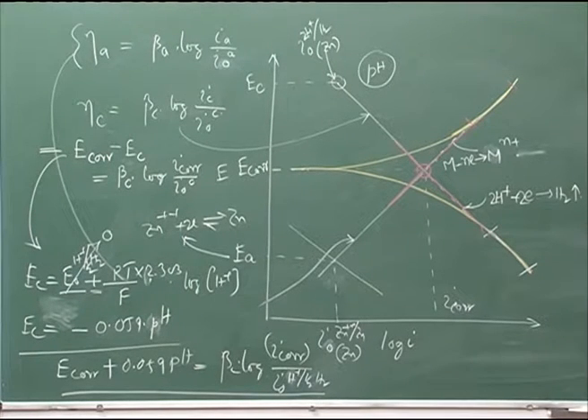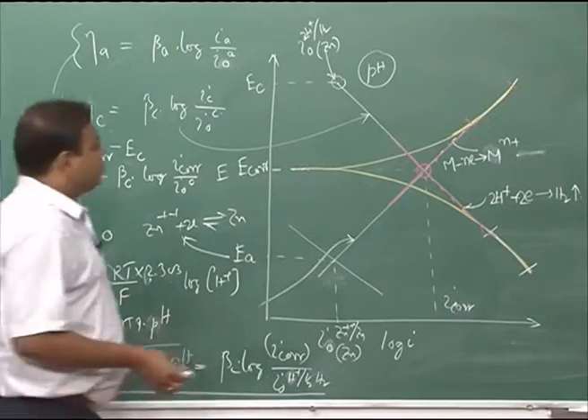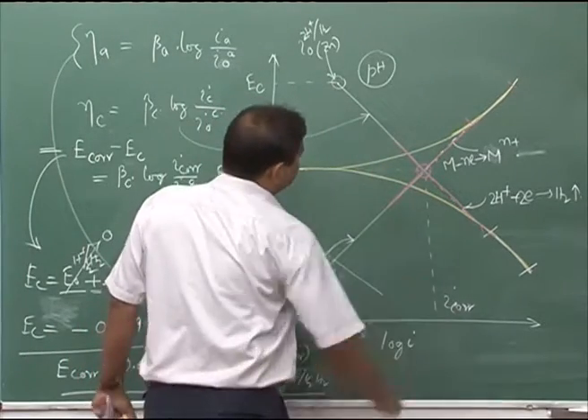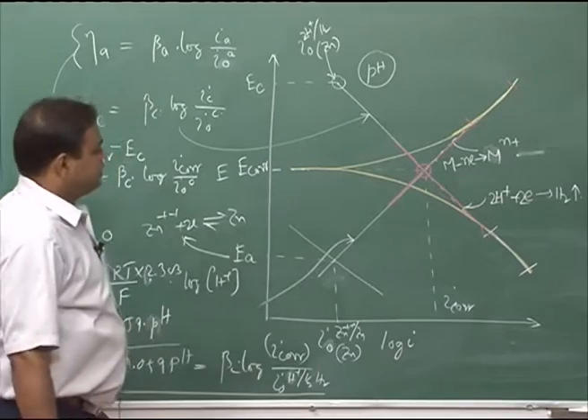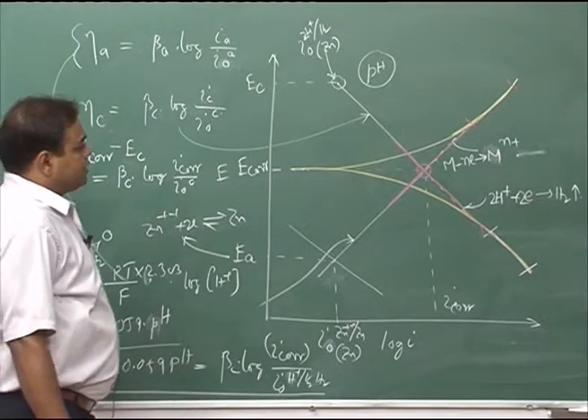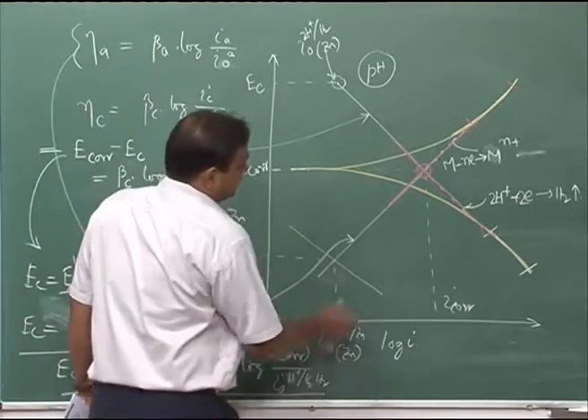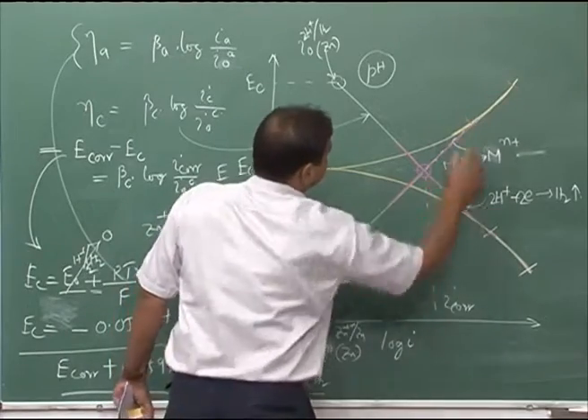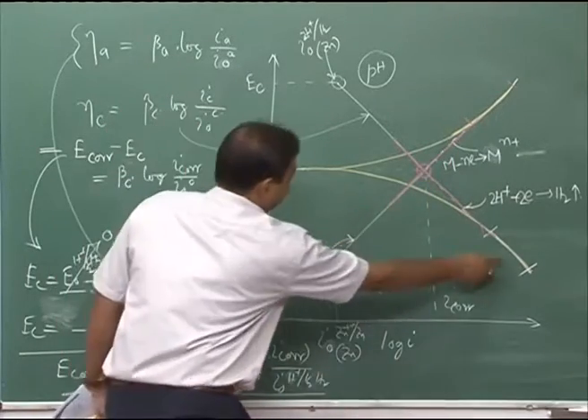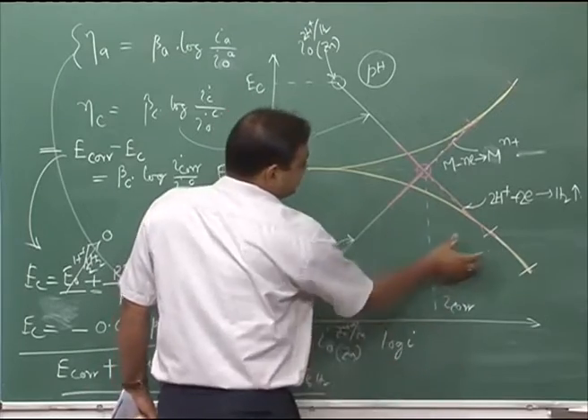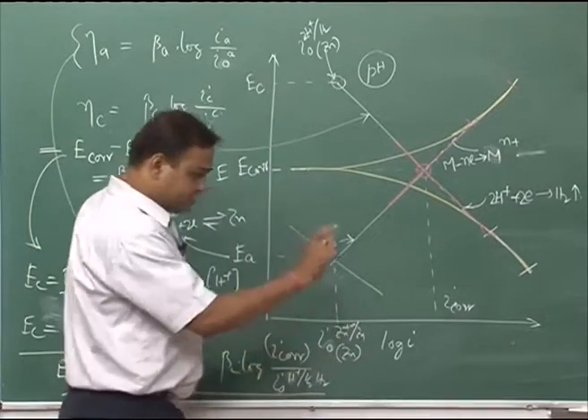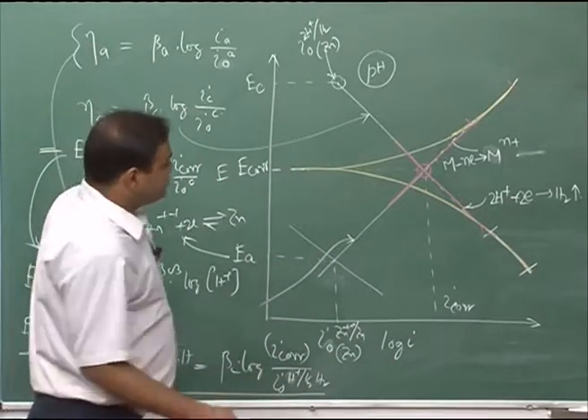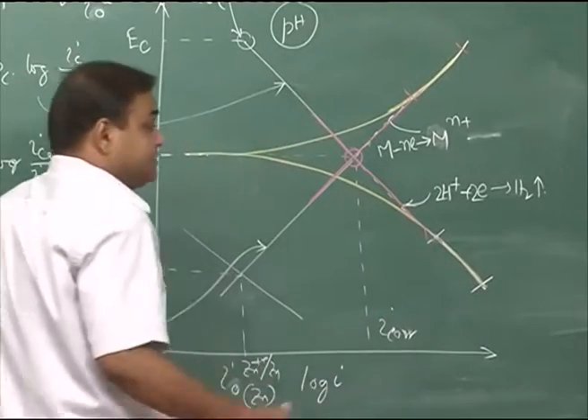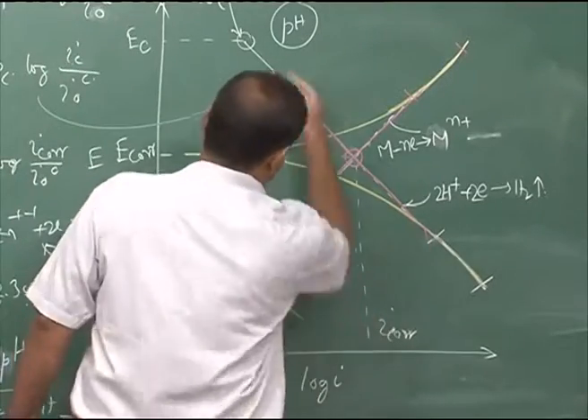Another limitation: when we consider this gaseous reaction as the cathodic reaction, the crux of this method is getting the linear part in the polarization graph. This is my polarization graph. In that part, this should be linear - that should be a linear part. If we do not have this linear part, then there is a problem, because we cannot extend it and find where we have it.